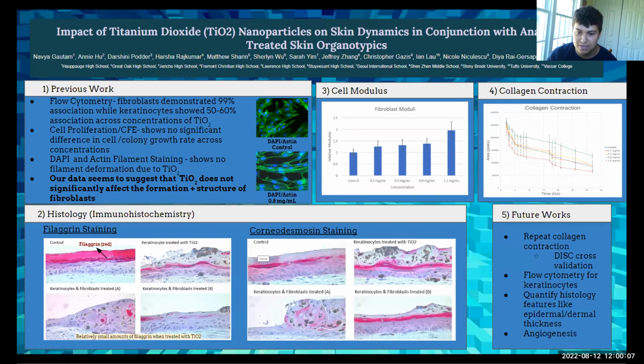So these early tests seem to suggest that TiO2 had very little impact on the ability of fibroblasts to support the epidermis, which was consistent with our histological analyses. We conducted immunohistochemistry tests by staining skin organotypics treated with TiO2 with filaggrin and corneodesmosin. For filaggrin staining, while the control depicted abundant amounts of filaggrin depicted by the red, less filaggrin was formed in keratinocytes treated with TiO2. Additionally, almost no filaggrin formed in the very aberrant stratum corneum in treated keratinocytes and fibroblasts A and B. We could therefore conclude that titanium dioxide had a profound impact on the differentiation through the regulation of filaggrin expression.